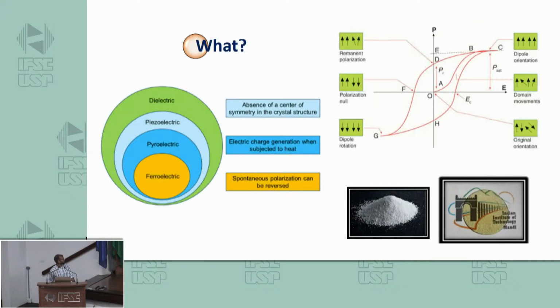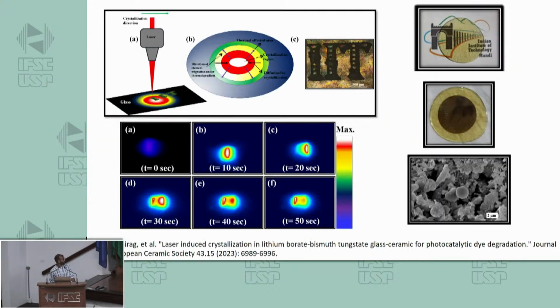So glass ceramics, especially ferroelectric materials, using pyro, piezo, and dielectric properties of ferroelectric ceramics, they are famous for non-linear optical properties, and they have a hysteresis loop of the polarization that varies with electrical potential. And as you can see in the picture, there's a powder of ferroelectrics, and it's very hard to recover and reuse once you use this catalyst for water cleaning applications. So I'm trying to embed this into the glass and make it glass ceramics. The next picture is transparent bulk glass ceramics.